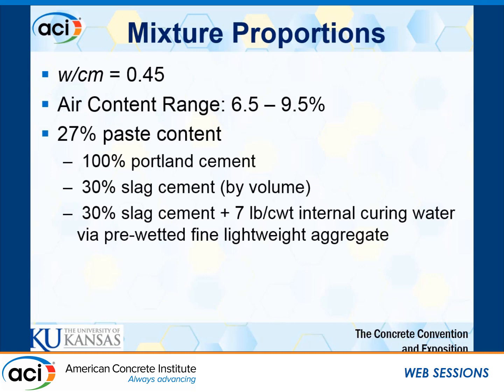Holding that same paste content, our next variable we looked at is doing a 30% replacement with slag by volume, and the third set is doing that 30% slag along with 7 pounds of internal curing water per 100 pounds of cementitious materials via a pre-wetted fine lightweight aggregate.